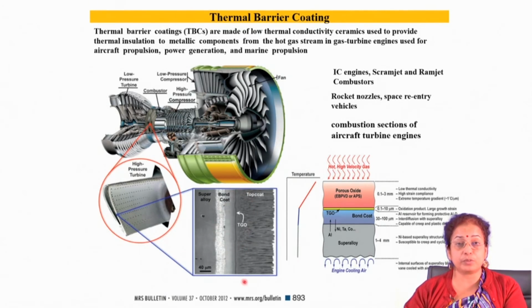Whenever you have the bond coat and top coat, you will find that gradually, when you expose the whole combination to the environment, the bond coat gets oxidized, because of the transportation of oxygen through the top coat, which is usually porous in nature. Porosities are desired in the top coat because the whole combination is usually subjected to thermocyclic stress. Whenever it is subjected to thermocyclic stress, a lot of stress is generated in the coating. So you should have a lot of defects in the coating, so that the stress is accommodated in the defect sites. But defects are also not good, because the presence of defects creates a chance of oxygen ingress. That oxygen usually reacts with the bond coat surface and forms the thermally grown oxide layer.